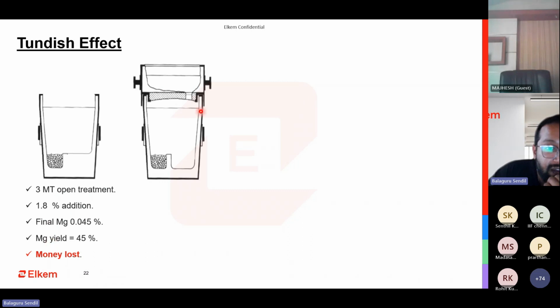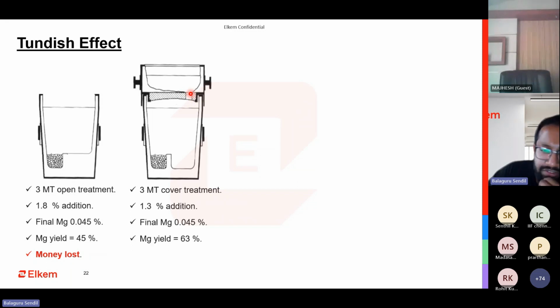But with the correct pocket hole designed, the tundish hole here, we were able to do the same with the cover treatment. The addition came down to 1.3 for the same amount of residual Mg, and the magnesium yield came all the way up to 63. So this is the advantage of having a properly designed ladle with a tundish, and we from Elkem can help you in getting this design exactly to your requirement.